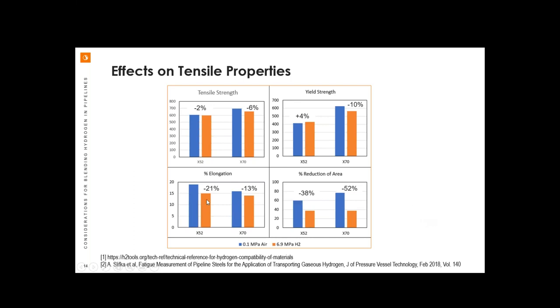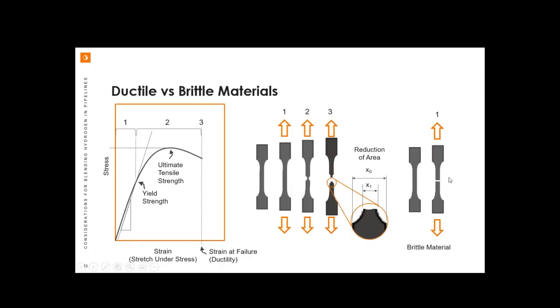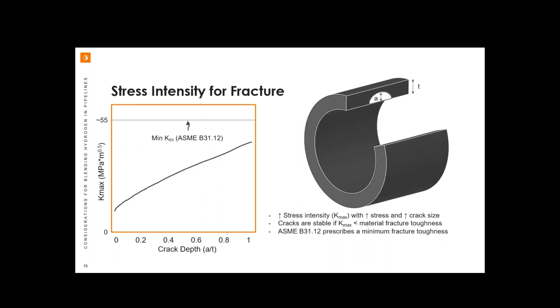I just want to underscore that even these embrittled values, 15% elongation isn't too bad. For example, this is about 38% reduction of area. So we are still more ductile. We're just moving towards this. And Jonathan's going to show the implications of that in some examples. Something else that's been noted with tensile samples is if you have a notch or some flaw and you're pulling that, the samples do a lot poorer in a hydrogen environment than air.